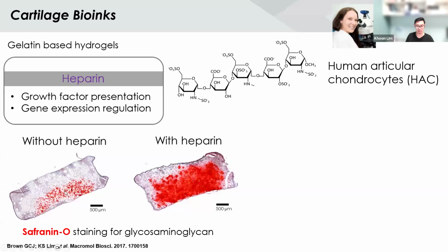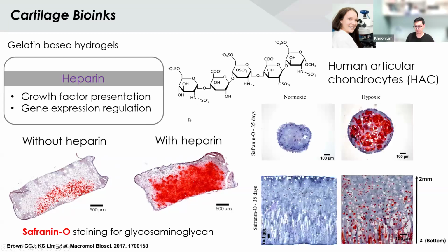So you can see the materials that we do not add heparin, the articular chondrocytes within them can't make tissue. If you now add heparin in them, covalently bound to the hydrogel, culture them up to 5 weeks, you can see abundance more of glycosaminoglycan, as evidenced as the red staining here, that the cells are now producing within this material. What we also found is that you can also control tissue formation based on how you culture these samples.